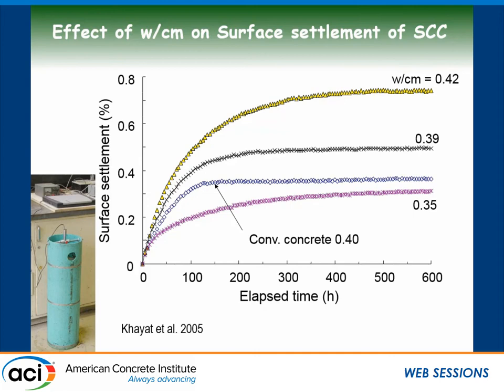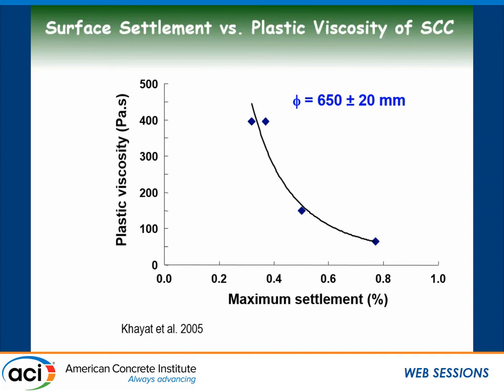We're very happy when we have only 4 points and we have a high correlation coefficient, but those are the four points that correspond to that experiment. You can see that there's a clear trend: the surface settlement decreases because you are building viscosity. As you are reducing the water cement ratio from 0.42 to 0.39 to 0.35, et cetera, for the same yield stress, slump flow, you are increasing the plastic viscosity, and that's what is responsible for reducing the surface settlement.